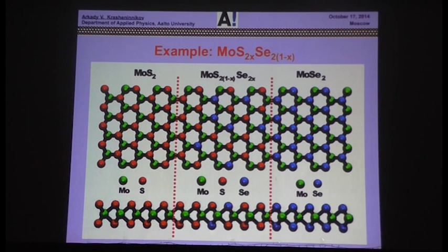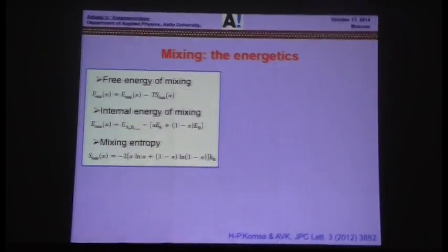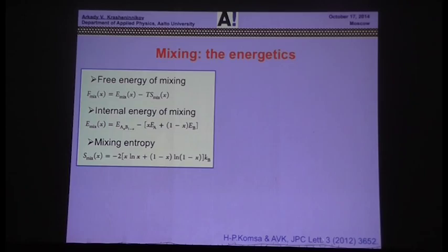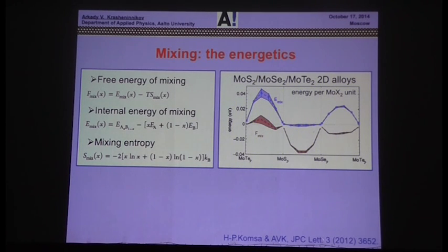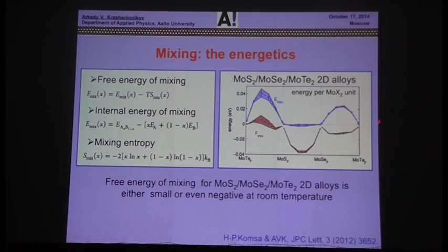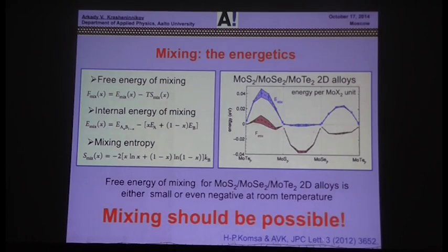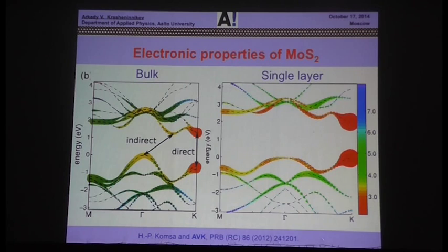Again, recall that the unit cell is more or less the same for molybdenum diselenide and molybdenum disulfide. And then we calculated the free energy, accounting for finite temperatures. Making a long story short, we found that the mixed system should be thermodynamically stable at room temperature. So mixing should be possible. Then the next question is electronic properties. I'd like to remind you that bulk molybdenum disulfide has an indirect gap, but a single sheet is direct.